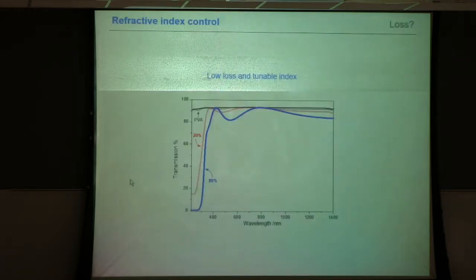And this is shown here, just calculations. In case you have a refractive index of 1.6, you see the oscillations, the maxima actually hit the transmission of the substrate or the neat material. In case you increase the refractive index from 1.6 to 2, you see the oscillations get deeper. Where the loss comes in is, and that's what people often forget, you still have oscillations when you have a lossy material, for instance, one that absorbs, but these oscillations do not hit the transmission of the substrate anymore. So like that, you immediately get a qualitative picture if you have a lossy material.